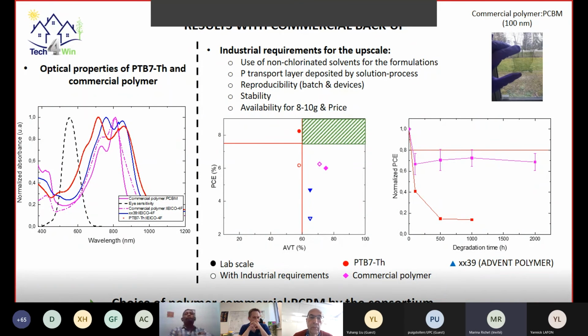But for the project, it's necessary to meet some industrial requirements, like the use of non-chlorinated solvents and a P-transport layer deposited by solution process. Reproducibility is always important, as are stability and the availability of materials. When we make devices with industrial requirements, we see a drop of efficiency for the PTB7-Th polymer to 6%. With the confidential commercial polymer, the efficiency is comparable between industrial requirements and lab scale, and we obtain an efficiency of about 6%.